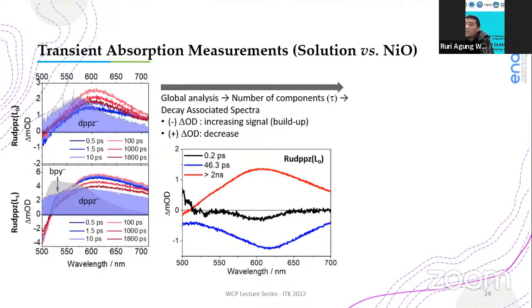So to quantitatively analyze the data, we perform global fitting to the transient absorption spectra, yielding the decay associated spectra like this. For example, for ruthenium L0, we have a sub-picosecond decay component, which is 0.2 picosecond, which reflects the contributions of intersystem crossing and intramolecular vibrational redistribution. And then we have the second component, at 46.3 picoseconds, which shows a build-up of signal at 600 nanometers, which can be assigned to intraligand charge transfer transition from the phenanthroline to the phenazine part of the DPPZ. And the final process, which is longer than 2 nanoseconds, indicates the return of the excited state to the ground state of the complex.